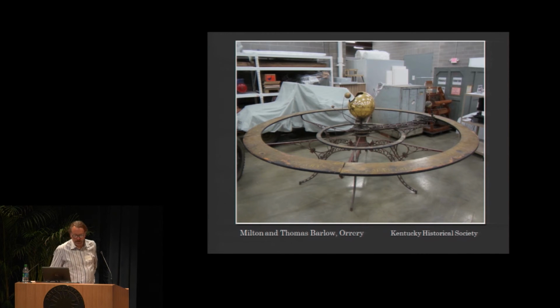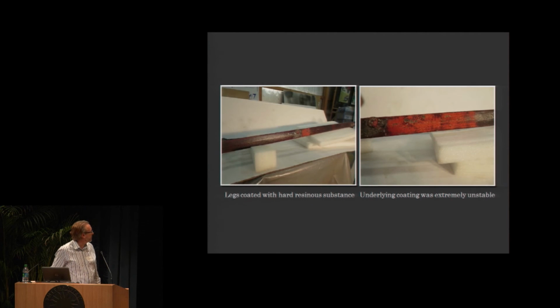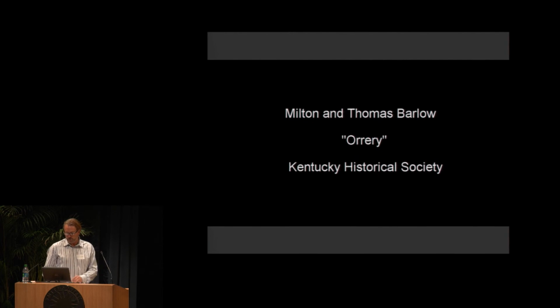Next up, we had an orrery, and I love orreries, but this one had been coated with epoxy on the iron legs, and I think it was to kind of adhere the paint that was becoming quite friable. So our task was to get this epoxy off and leave this kind of friable, unstable paint coating underneath it. It was a hard resinous substance. I'm not exactly sure if it was epoxy, but it was very, very resistant to solvent cleaning. So again, we tried dry ice, and we found the effects were just great. Let's see if this video will run.